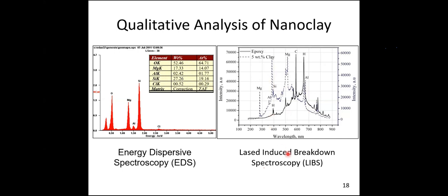So from that laser induced breakdown spectroscopy also, we could see the epoxy has hydrocarbons, wherein the epoxy clay has magnesium, silicon, aluminum. So these are the alumina. So these are the main composition of the clay, which we have confirmed from the EDS and LIBS, energy dispersive spectroscopy and laser induced breakdown spectroscopy. So we have confirmed the composition of epoxy and clay.